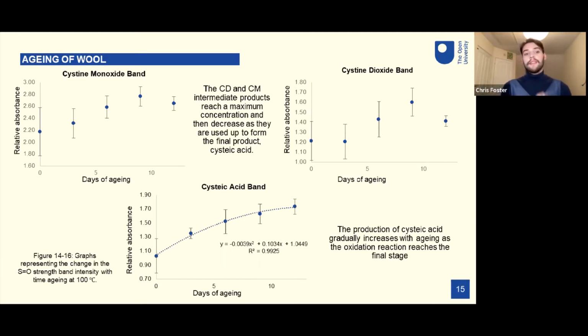So as we see for the cystine monoxide and dioxide, there's a slight increase followed by a decrease. This seems counterintuitive, but it actually correlates with literature. And the reasoning for this decrease is because these are intermediate products, they're not the end point of the reaction. It reaches a point where there's a maximum concentration, and then it's all being used up then to create the final product. And this coincides with what we find with the cysteic acid band showed at the bottom. And this just has a gradual increase of product, which is what we'd expect.